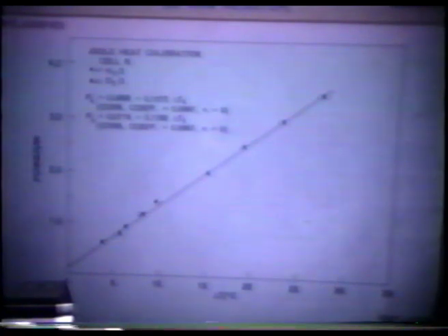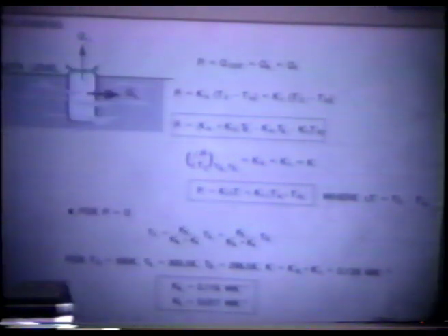and that is some heat does escape through the top of the cell. It does not go through the water bath. And you can model that and explain why the intercept is not zero. Most of the heat does flow from the cell to the water bath, but there is always some heat that goes from the cell to the room temperature air. And you can break this up into two effective constants. On top, that's why we have a T there, and go through some algebraic calculations, which I don't take time to do, shows all the details here.